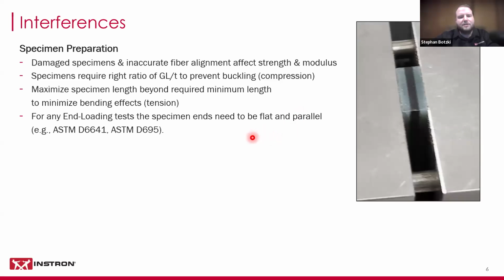If you're doing end loading tests where your specimen gets end loaded like ASTM D695, or you have a combined loading test like the ASTM D6641, you need to make sure that the ends of your specimens are flat and parallel, because that's obviously one of the major ways here in the combined loading, for example, how you introduce the load. So if your ends are not flat, you're going to have an uneven load introduction into your specimen. You might also have failures where you did not want them. So you don't want them to fail here at the ends.